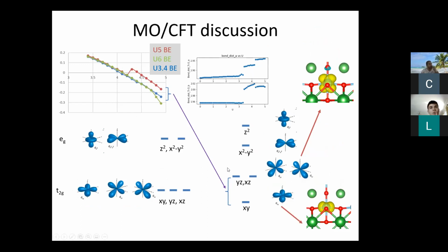It's a small, neat demonstration: I ran a few different calculations from different starting points, and I actually had two different orbitals, and they weren't the same energy. So for a given value of 4.5, the polaron formation energy was different. This was due to the higher energy state that formed here. In this case, it ended up being a combination of the YZ and XZ orbitals compared to the XY orbital here. You break the degeneracy because you bend the octahedron down, and you have different polarons formed. They probably would have different migration energies, but I only had time to test one of them.